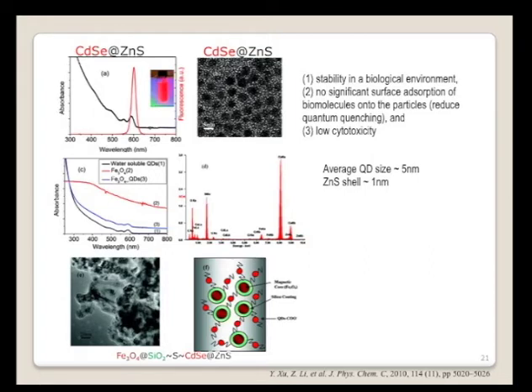This red curve is iron oxide, not much absorption. Here are the coated quantum dots. You still see it here. We also did the EDX to check all the elements, because after synthesis we wash this with acid or water, to see if all these elements are still there. Okay, we found exactly all these combined together.